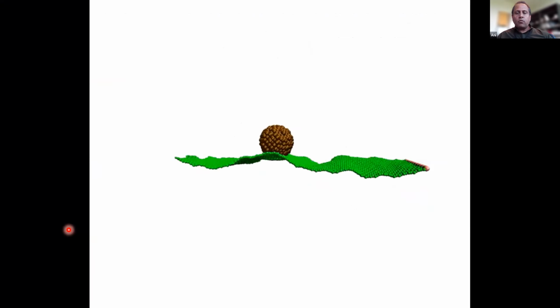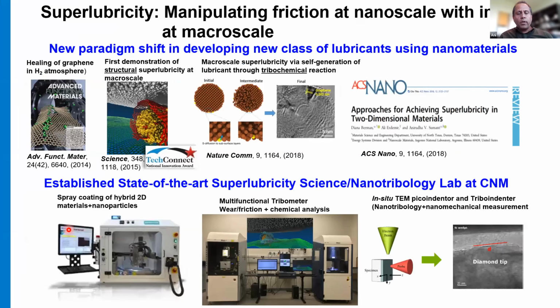So here it is now. That's where we show very interestingly that this forms a ball bearing, and the nanodiamond is free to move inside, acting as a kind of nanoscale ball bearing. Going forward, we talked about this in different systems, including molybdenum disulfide and nanodiamond. And we now have the superlubricity lab here at CNM that can study wear and friction at the macroscale as well as at the nanoscale, using this picoindenter, so that we can see in situ in the TEM while we are sliding different tips of different materials against each other.